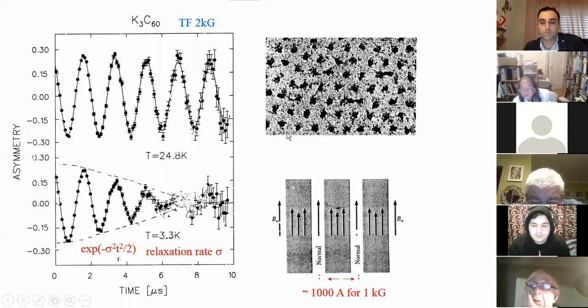So we do millions of this event and add up together. So that means if there is a magnetic field inhomogeneity, that would contribute to cause this damping of the field precession. And so by measuring this damping, we can also determine how much the field is changing within different positions.